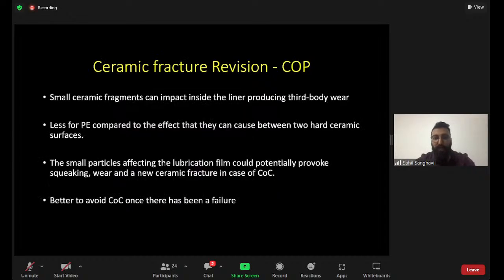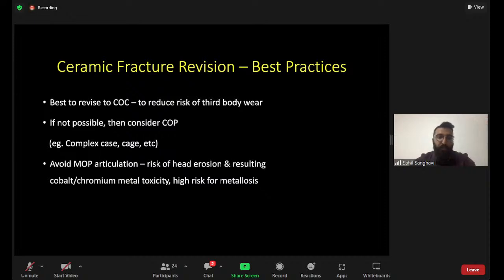So when you have ceramic fracture revision, ceramic on polyethylene is also a viable option. The best practice for ceramic fracture revision would be to revise it to a ceramic on ceramic bearing surface to reduce the risk of third body wear. If not possible, then you can consider ceramic on polyethylene, for example, in a complex case or when you need to use a cup cage. And you must definitely avoid metal on polyethylene articulation because of the risk of head erosion resulting in metal toxicity or metallosis.